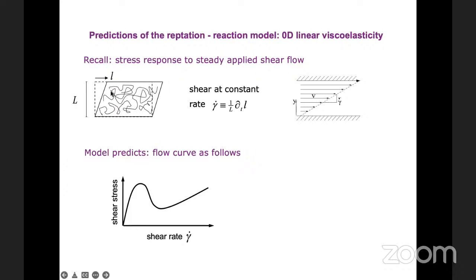So in other words, they've got knocked flat somehow in the flow. In measuring and characterizing the shear stress, it tends to be maximal when the orientation is 45 degrees. Once they get beyond that, you effectively don't have anything to bite into in terms of cutting through the molecules in this direction to give you a shear stress. And so the shear stress is then much lower. So that's an argument in chain-like systems, and a similar argument applies in liquid crystalline systems as well.